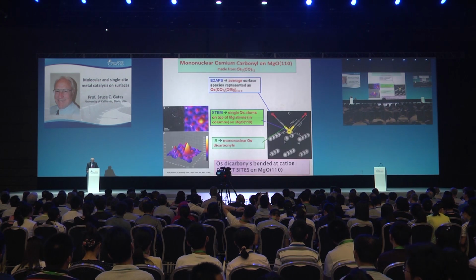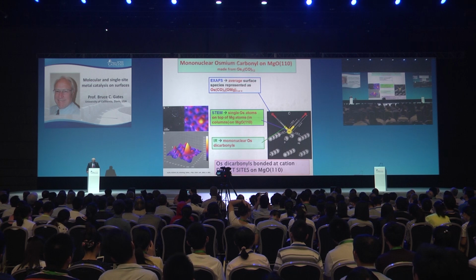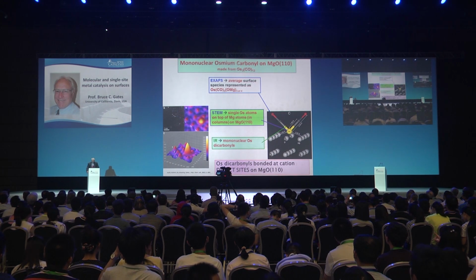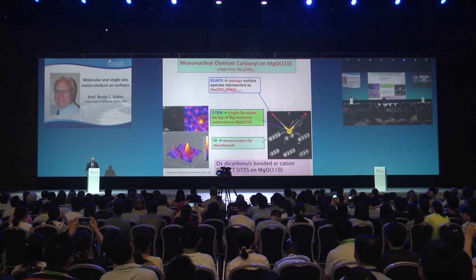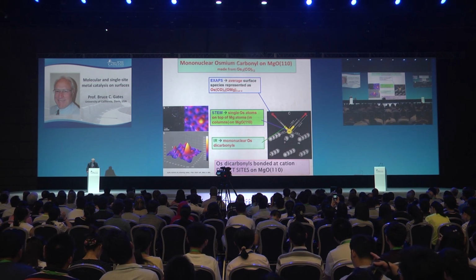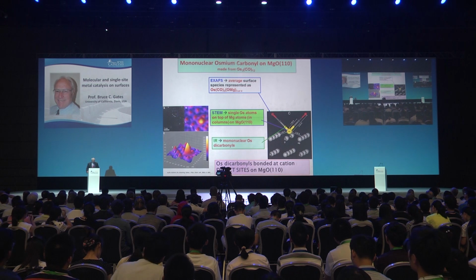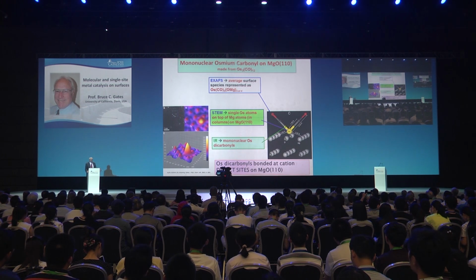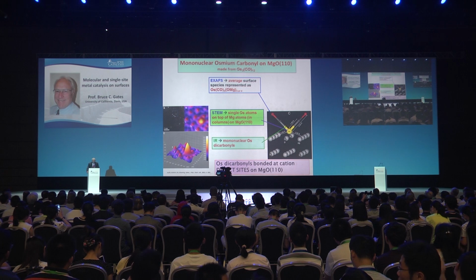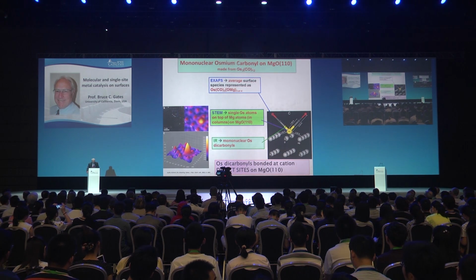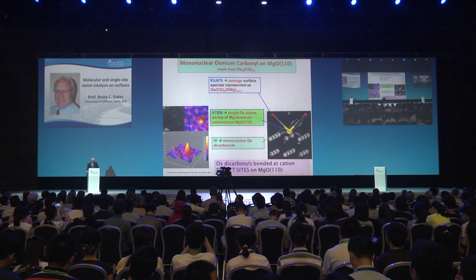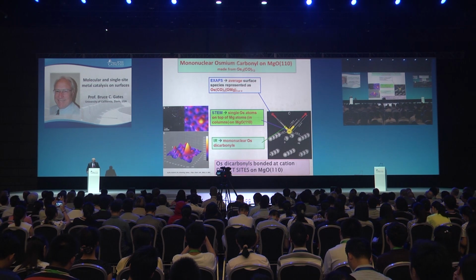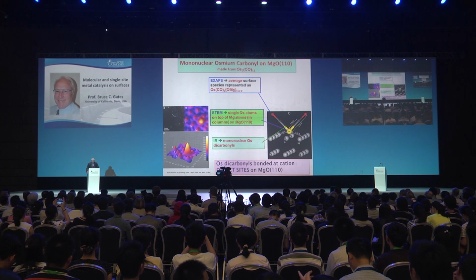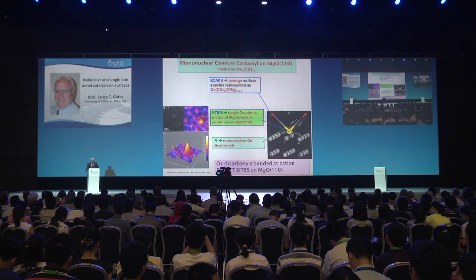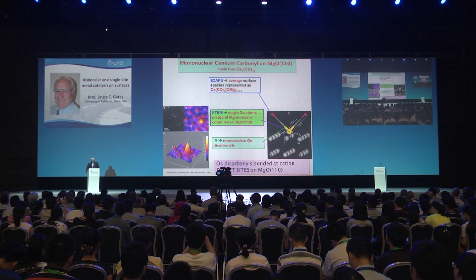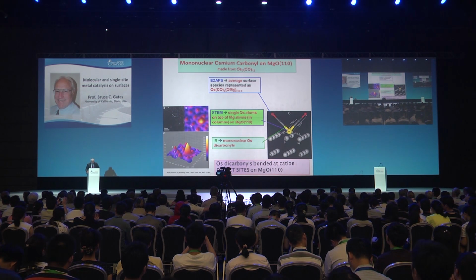Let's focus on one face, the 110 face of the MgO powder. And this is an osmium complex—I don't have time to tell you how that was made, but it's this mononuclear osmium complex. The important point is that one looks at that support surface, MgO 110, and it provides a vision so that one's looking down on columns of magnesium and oxygen atoms. What the images show is that the osmium is directly above magnesium.